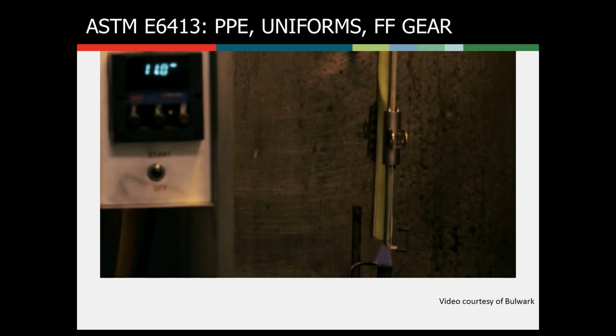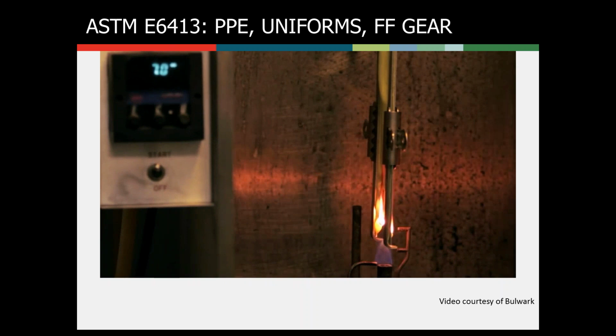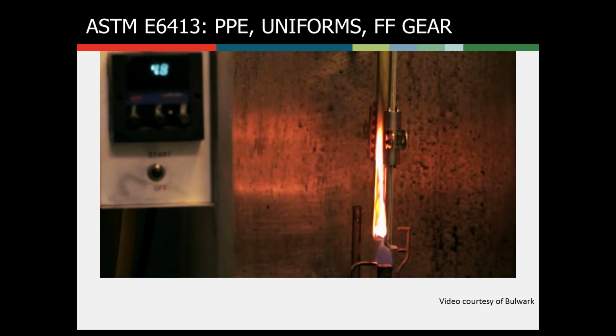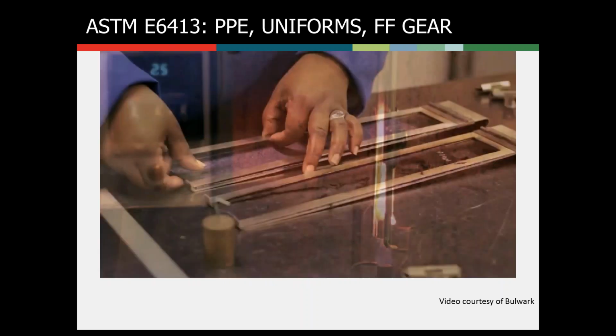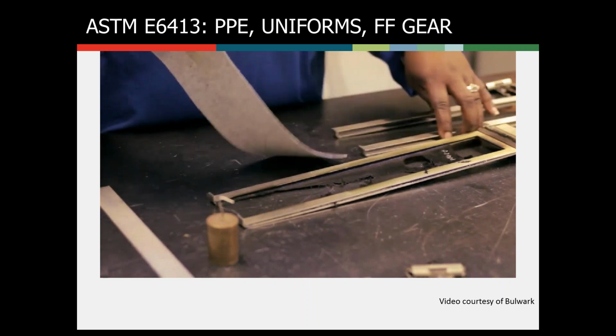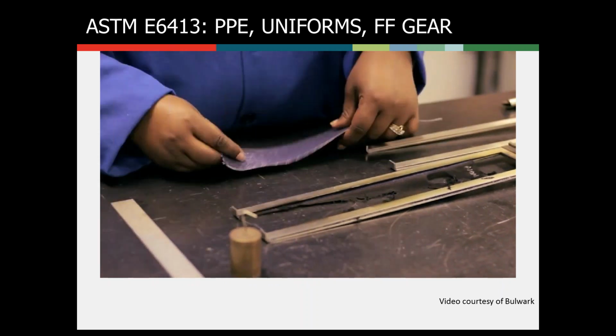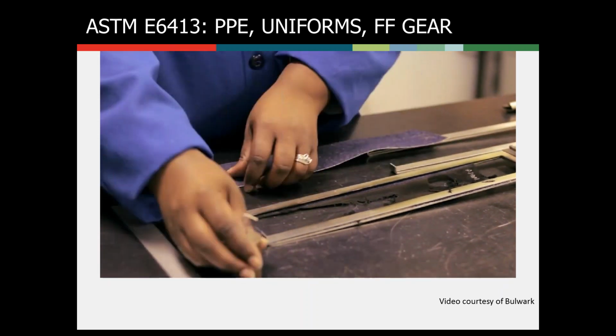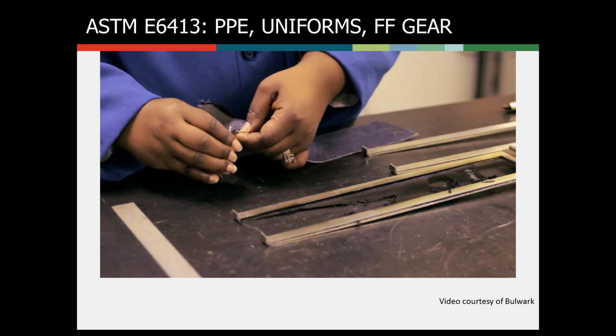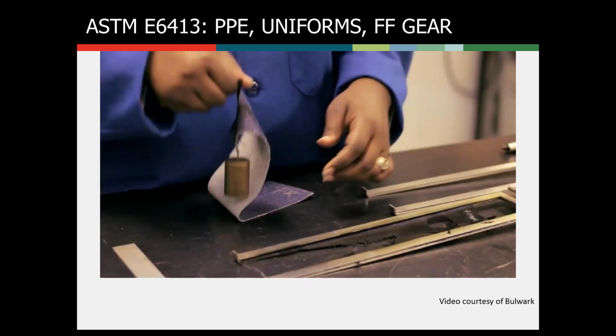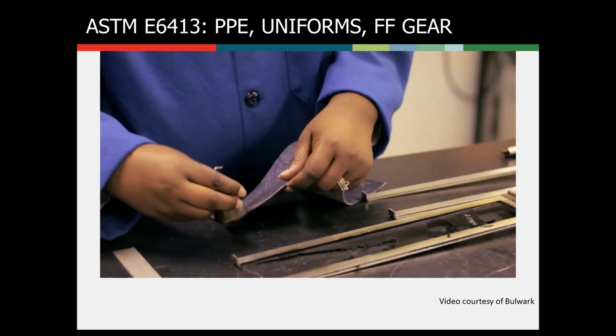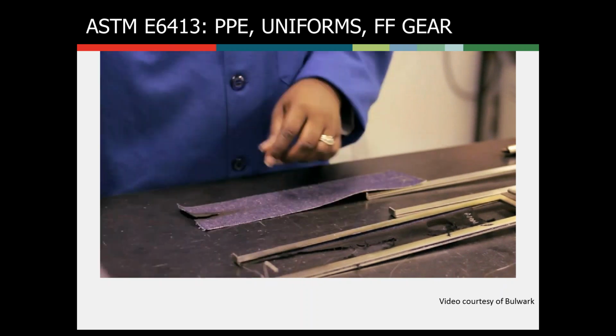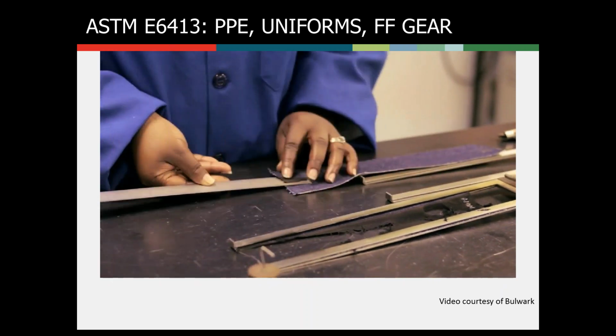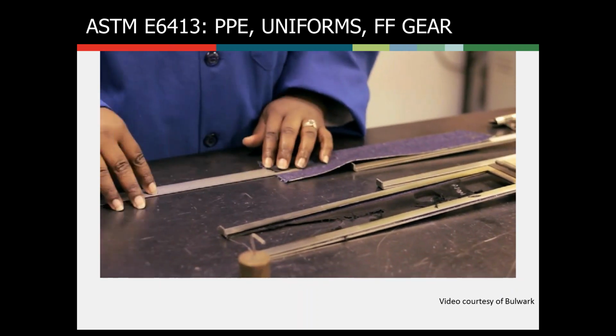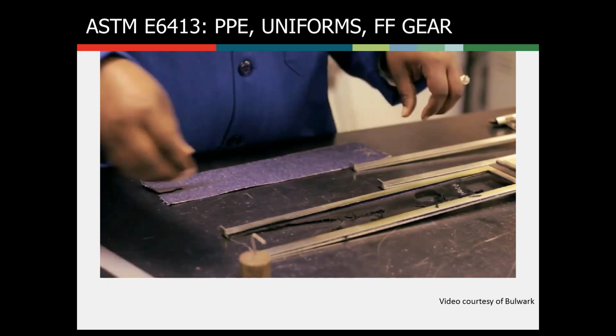Here's a final test. This is a polymer-based material, so it's going to act much differently. You can see it kind of melt and move away from the heat source and go up. Once the test is done, you're going to take a look at the char length. Char length is measured by just the distance that the flame burns up the specimen. In this case, you've got a very small char length, on the order of 1 inch for that FR denim material.